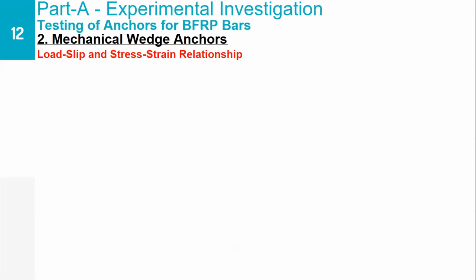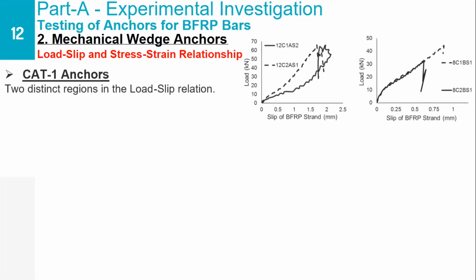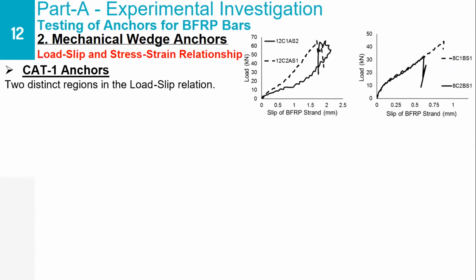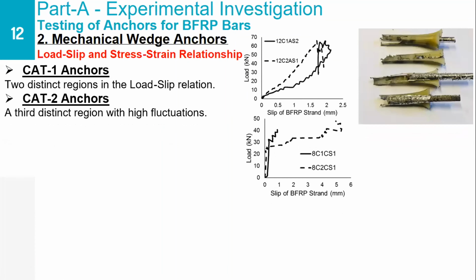Now we'll also take a look at the load-slip relationship as well as the stress and strain relationships of these mechanical wedge anchors that have been tested. Two distinct regions have been obtained in the load-slip relationship, noted by the change in the slope of the curve. This initial slope is due to the seating process of the anchors inside the barrel, and thereafter the slope becomes steeper after the initial seating of the anchors inside the barrel. For the category 2 anchors, there was a third region in the load versus slip relationship, and that was due to the plastic deformation of these anchors that was observed after the test.